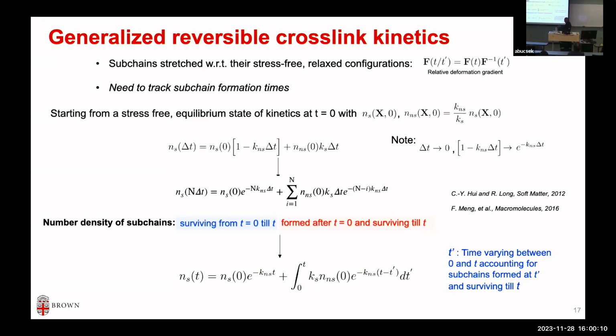Before I get to the second mechanism, which is all about this network behavior coming from these dynamic crosslinks that are forming and breaking, right? If I want to define the number of subchains that are actively forming crosslinks at any time, going from time 0 to delta t, this is whatever that linear first-order kinetic equation I showed you, the same equation: forward reactive, backward reactive. But if you take the time step to be very small, if you remember from mathematics, you can convert a linear relation into an exponential relation. The exponential series expansion of e to the power x is 1 plus x. So you can reverse it, convert that into an exponential function, and go from time delta t to any time t. And the exponential allows us to convert this idea into a nice integral.